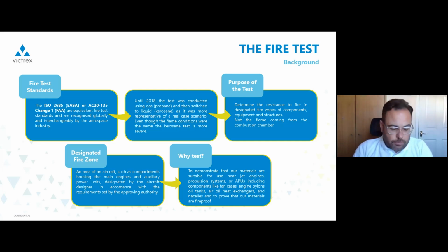One thing I would like to mention here is that until 2018, the test was done using propane as fuel. I think that had to do with how easily a lab would have access to propane. Since then, the change was made and we switched to kerosene, even though the conditions like the flame temperature, heat flux, and the time of the test were the same. Using kerosene actually made the test more severe, because kerosene is a liquid as opposed to propane, which is a gas. So somebody will then say, okay, why do you do this test?